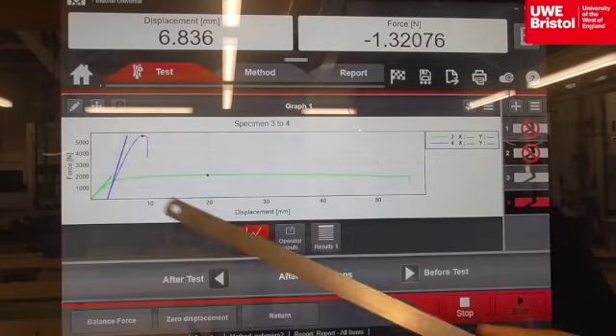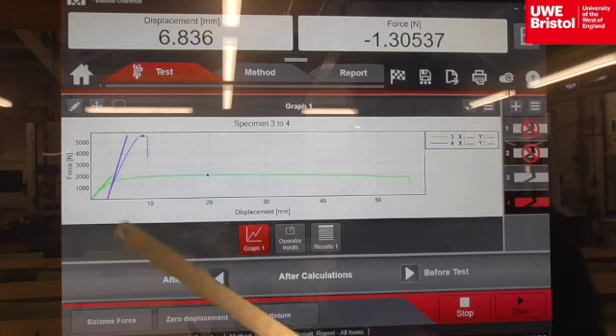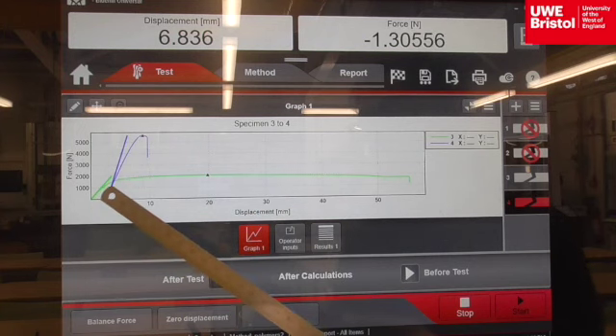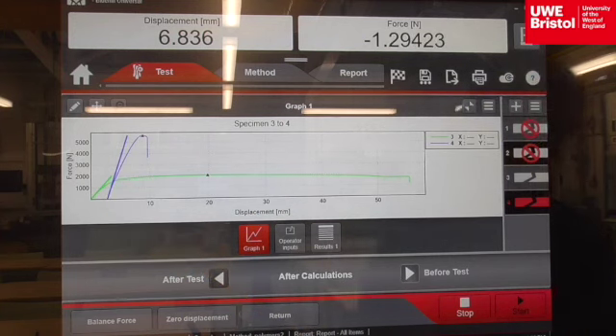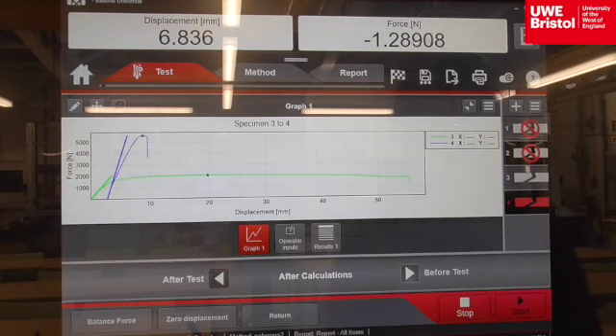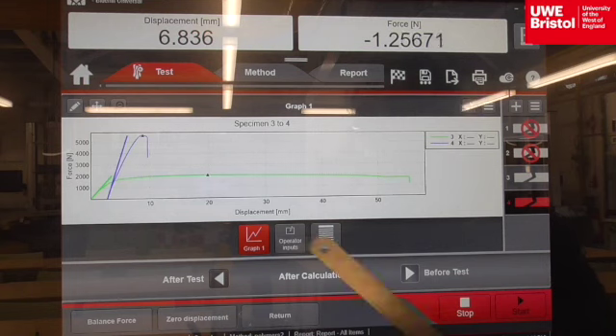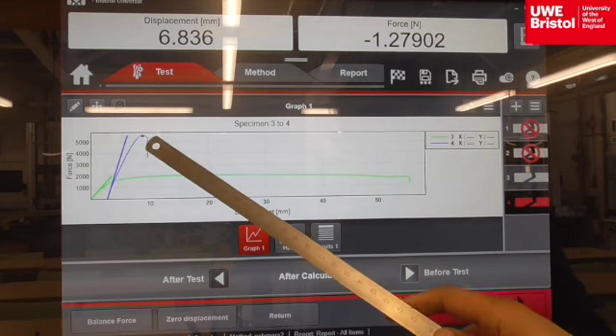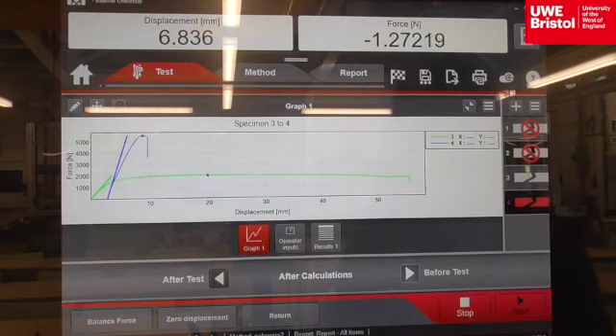The glass-filled nylon is the blue plot, and compared against the green plot of standard nylon, the glass-filled nylon has predominantly taken on the properties of the glass within its matrix, and so it's resulted in higher strength with little ductility. Strictly speaking, the mix between the polymer and the glass fibre makes this a composite material.